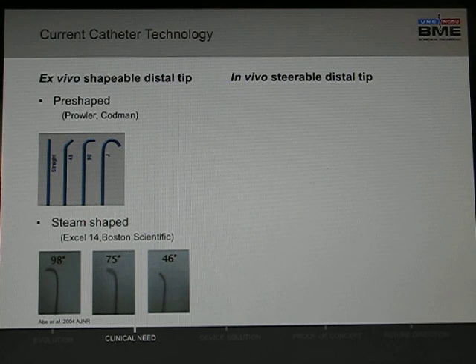The ex vivo shapeable comes pre-shaped like these that can be chosen at the discretion of the interventionalist. If these do not meet their needs, the distal tip can be steam-shaped to various orientations. These series of images show the catheter tip loses its original orientation once inserted coaxially through a larger diameter catheter, and even more so once a wire is passed through and manipulated.